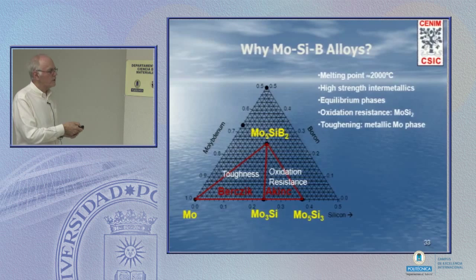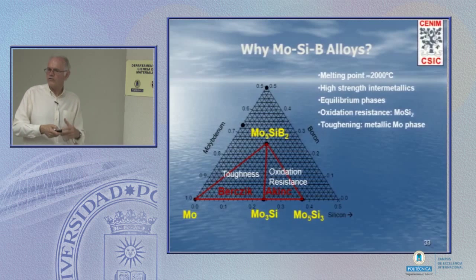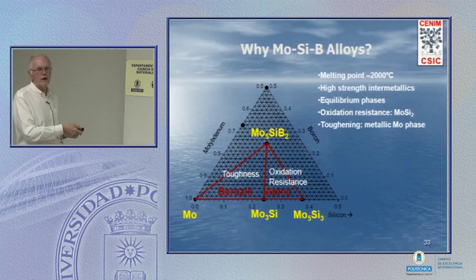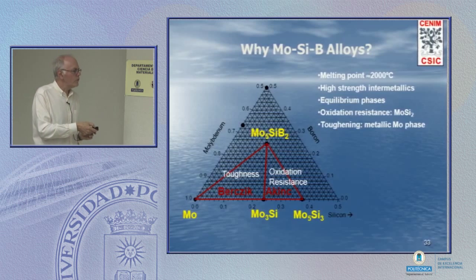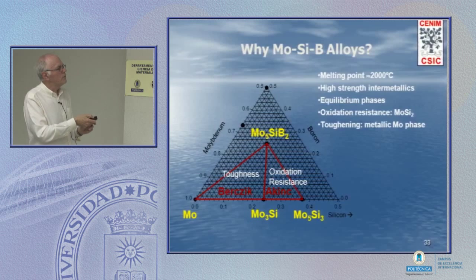Here's molybdenum, single phase, a very bad oxidation resistance. That's why we don't find molybdenum used very much as a structural material. Here's Mo3Si, here's Mo5SiB2, both very strong phases at high temperature, both wonderfully oxidation resistant. By looking at alloys with this sort of composition, we'll have a three-phase mixture, which will give us toughness. The more molybdenum we have, the higher the toughness. The more of these intermetallics, the more oxidation resistance. And so the game here is to balance these equilibrium phases, have a balance such that we get a balance of properties.